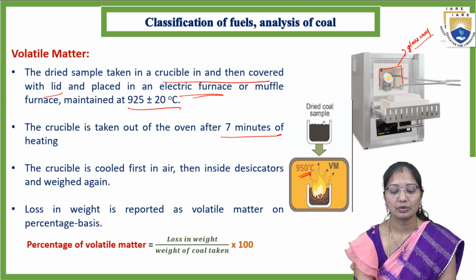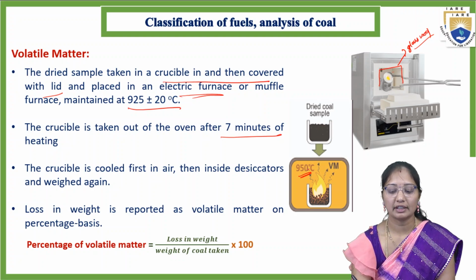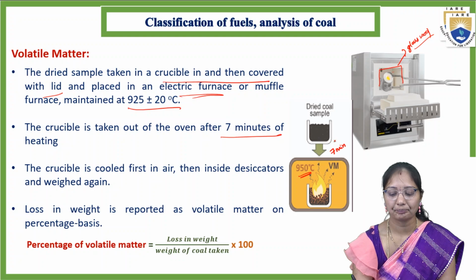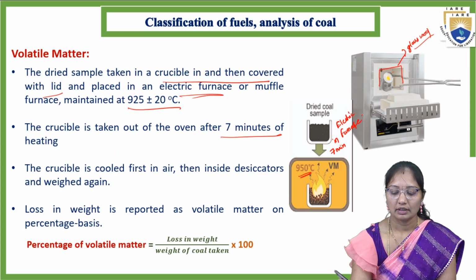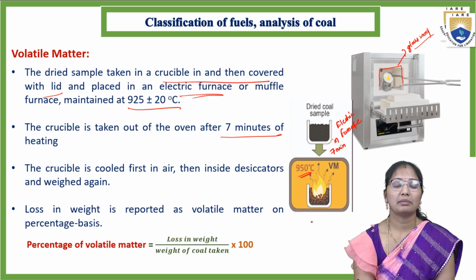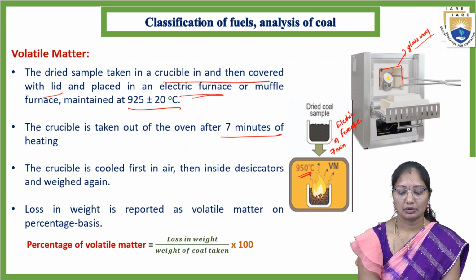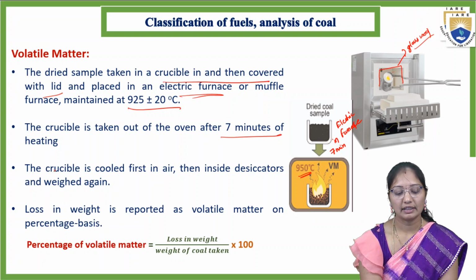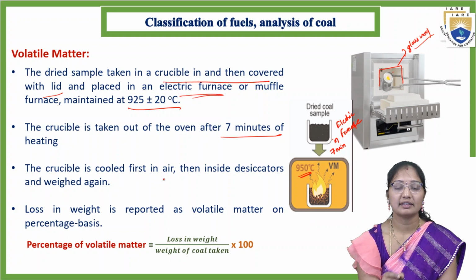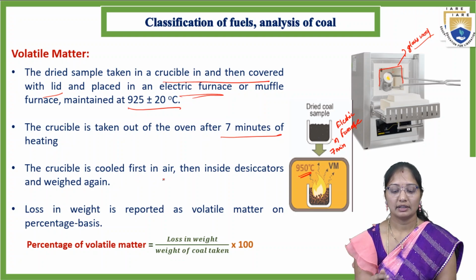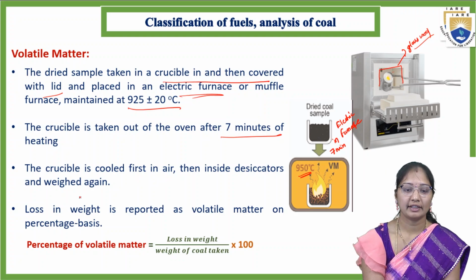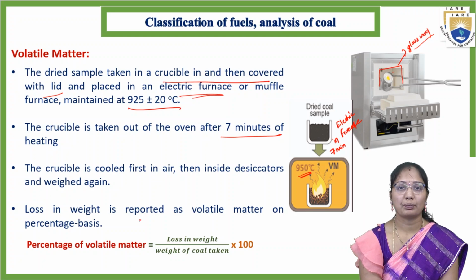This is the dried coal sample we are taking here. It is maintained at 950 degrees centigrade for 7 minutes in the electric furnace. The resultant is volatile-matter-free coal. Then the crucible is cooled first in air, then inside the desiccator, and weighed again. The loss in weight is reported as volatile matter on a percentage basis.